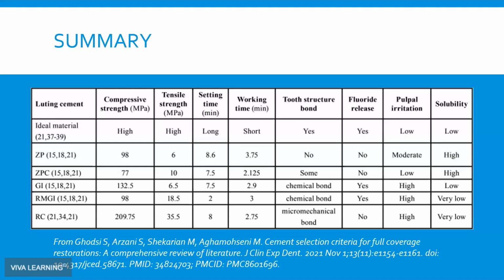Going from 10 to 18 for a resin, or a 6.5 to 18.5 from glass ionomer to resin modified glass ionomer is certainly clinically significant. And doubling that, essentially going from a resin modified glass ionomer to a resin cement to 35, 36 is, I think, at a point where no longer are you just seeing, let's say, debonding kind of failures. You're seeing failures that involve the material itself or even the tooth structure, like a fresh fracture somewhere else on the tooth other than the bond. So I would say resin cements represent close to meeting the goals of the ideal cement. Setting times are a little variable. Obviously, each one's depend on each manufacturer and what they're aiming to do with their cement. Working time also totally depends.